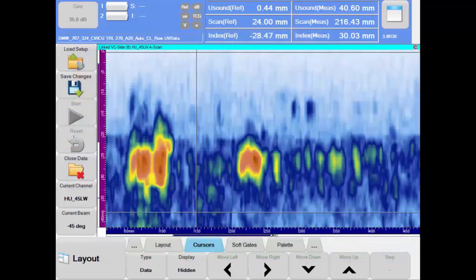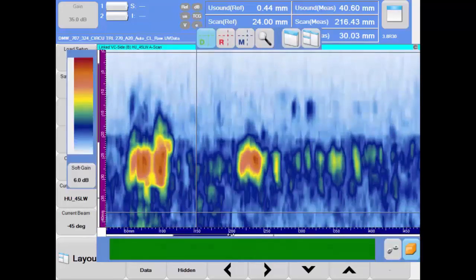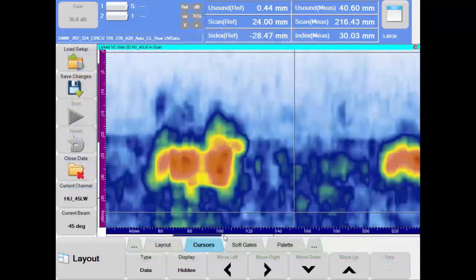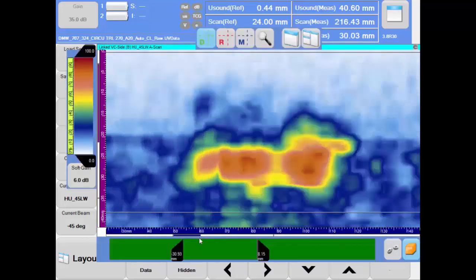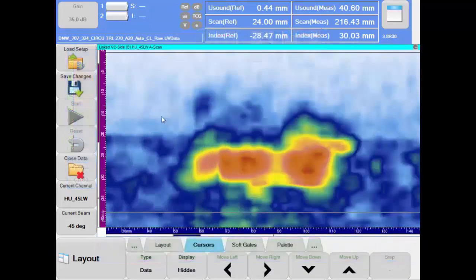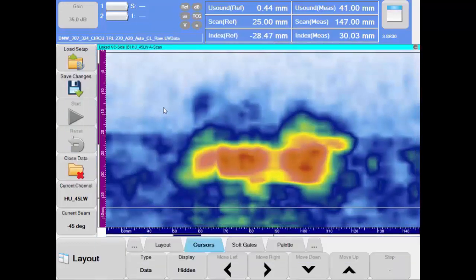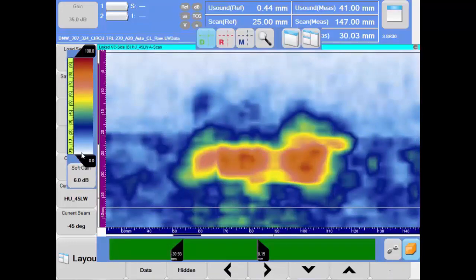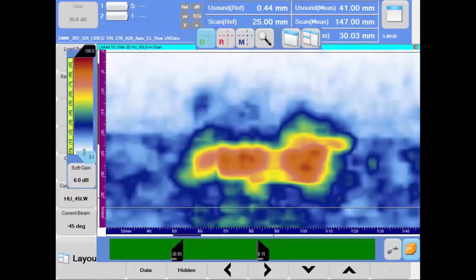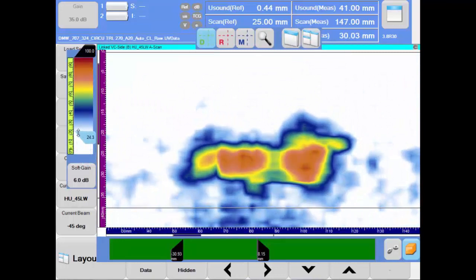First, it is useful to zoom in on the region of the indication. We can see a large high-amplitude corner trap indication at the ID of the specimen and some smaller amplitude signals above that. We will use the corner trap to determine the length of the crack. And as mentioned in a previous example, we will use the 6 dB amplitude drop technique.